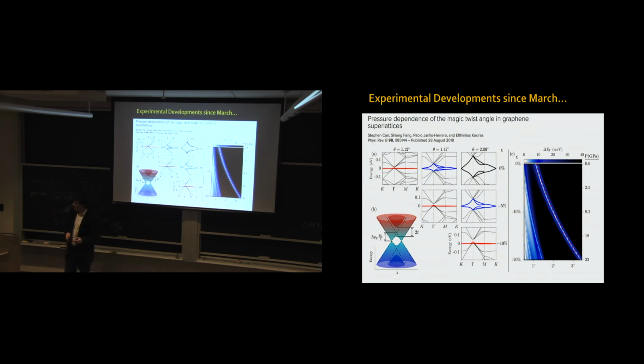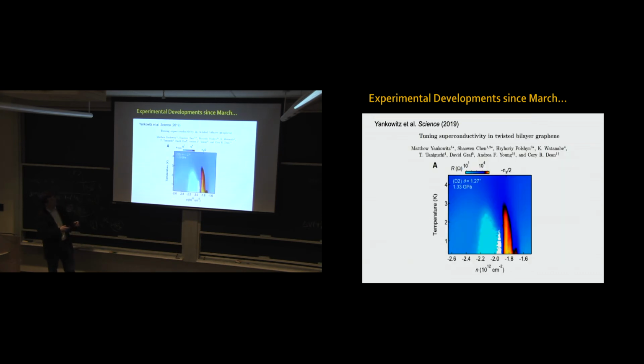And what this experiment at Columbia did is they had this device. The first thing they did was make a device at the magic angle, and they saw correlated insulators and superconductivity, reproducing our results. Then they made a device with a slightly larger angle, 1.27 degrees, not 1.1 plus or minus 0.1. No correlated insulators, no superconductivity. Then they applied the exact pressure we calculated, and correlated insulator and superconductivity appeared.